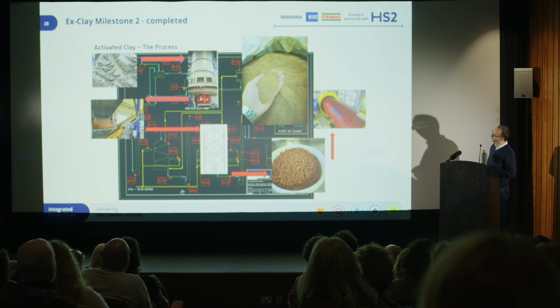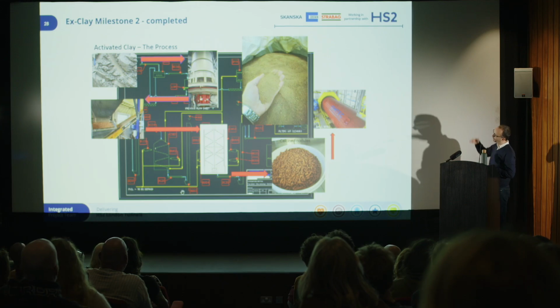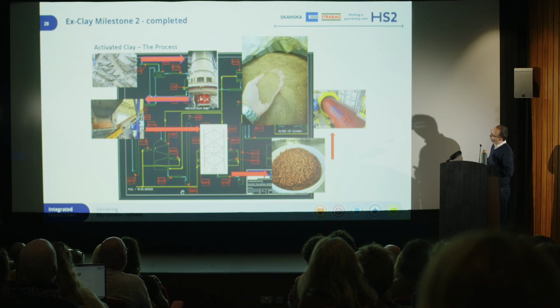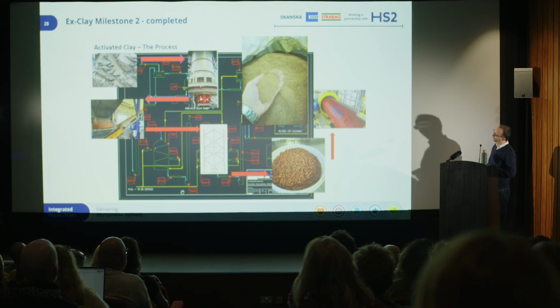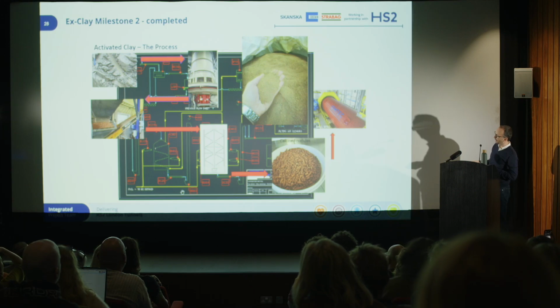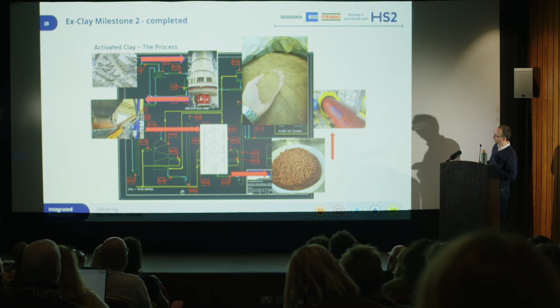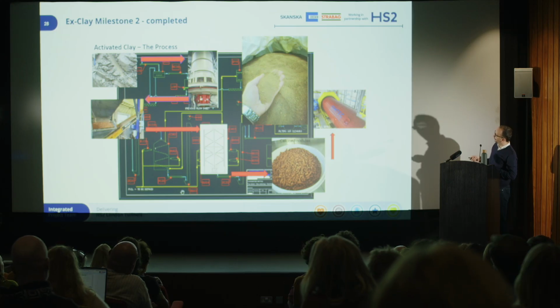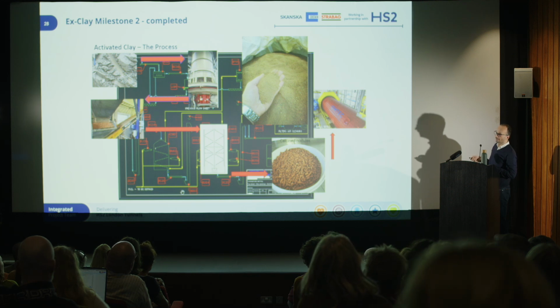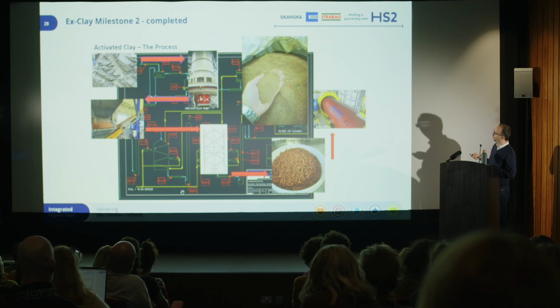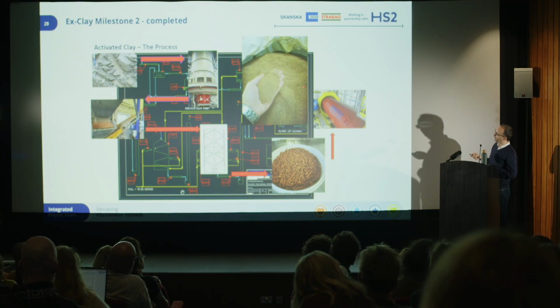Just to give you schematics of how the facility looks, this is where the pictures come from. So you've got the clay going in that tower, which is compressing it, exactly as Play-Doh. It comes out, goes into the drying facility, then it goes into those stages down there. So it goes through all those stages for heating, which is the calcination process. It comes out with a different color than where it started. And then it goes into this facility here, which is your normal cement grinder, but this is smaller, specific for the calcined clay, and comes out as this powder ready to be used in concrete. Of course, we have to define how fine the powder will be based on the British standards, so we can make sure that we comply on that front as well.